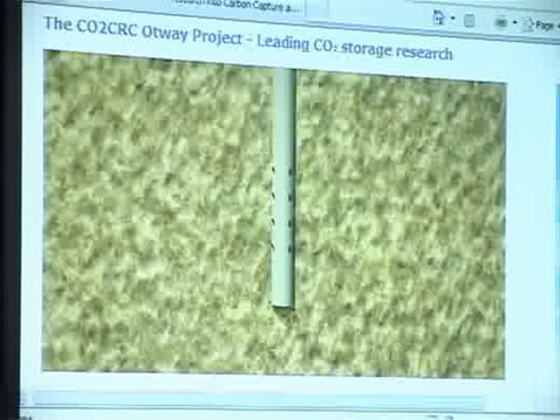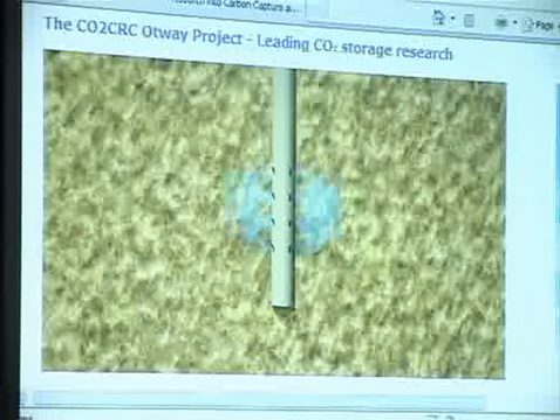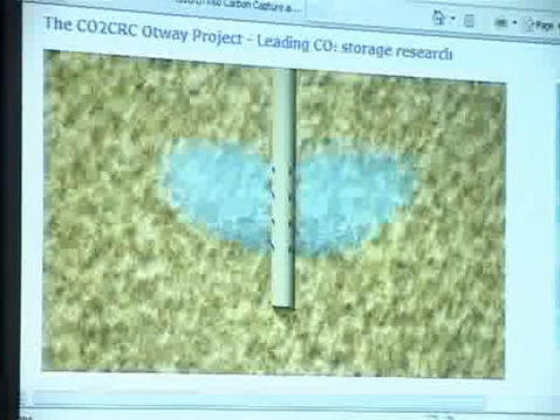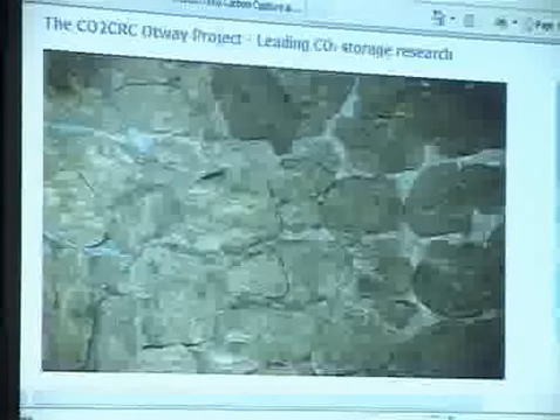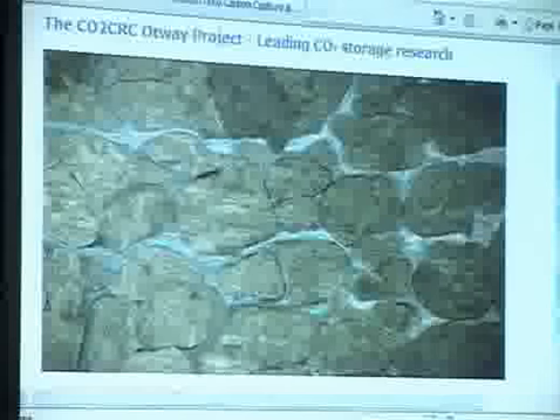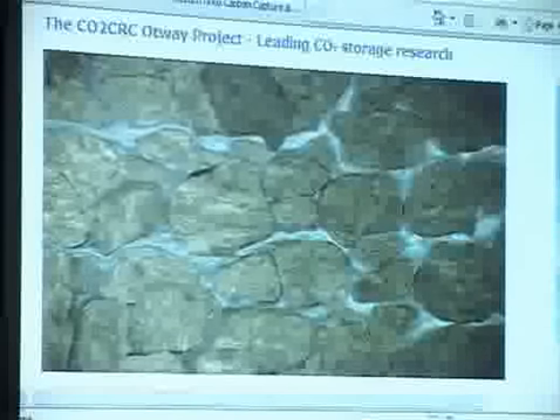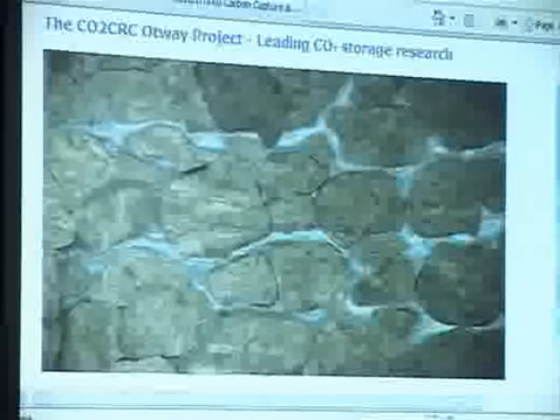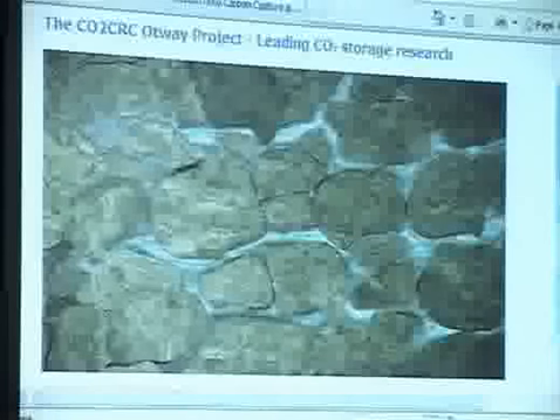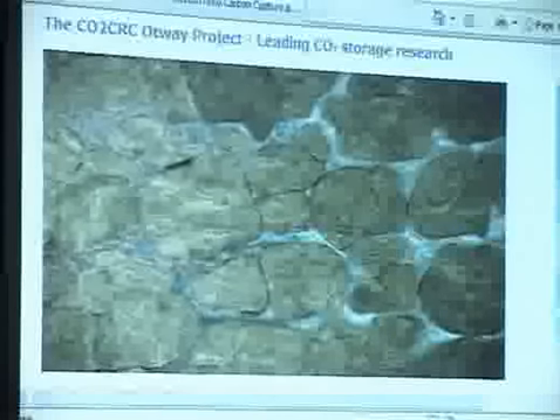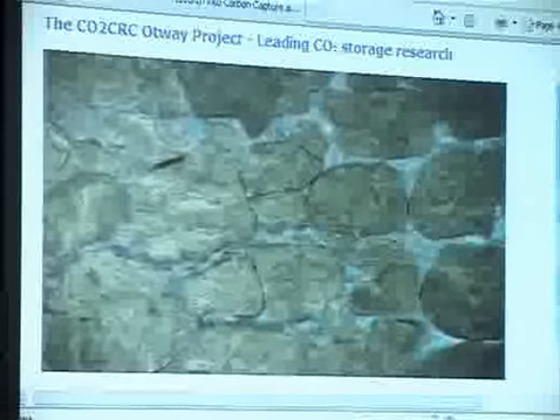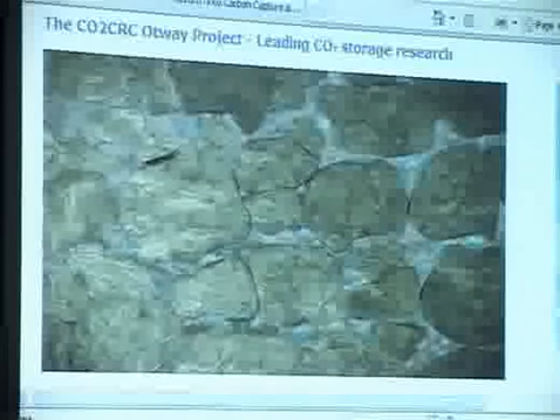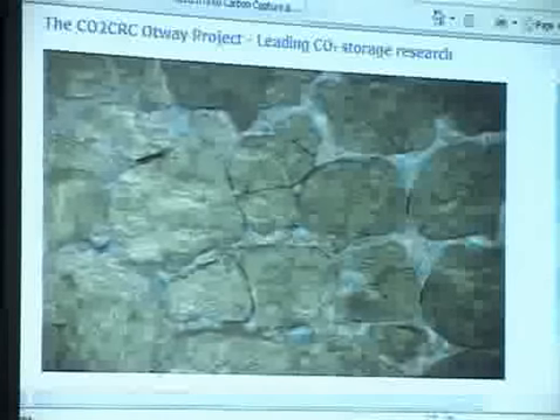A relatively small amount of pure CO2 was then injected into the formation to mimic a commercial CCS operation. After a period, formation water saturated with dissolved CO2 was re-injected into the well. The injected formation water breaks up the mobile CO2 plume, leaving residually trapped CO2 permanently stored in the pores of the rock.